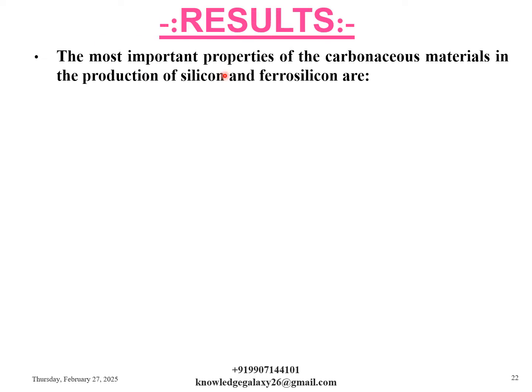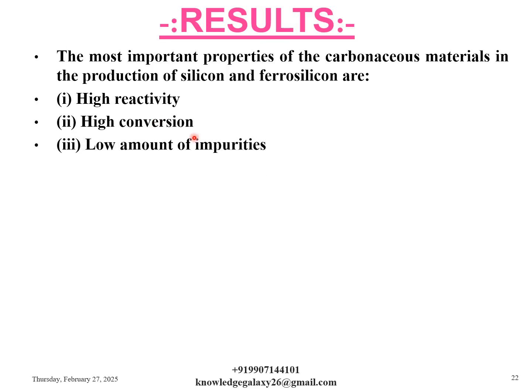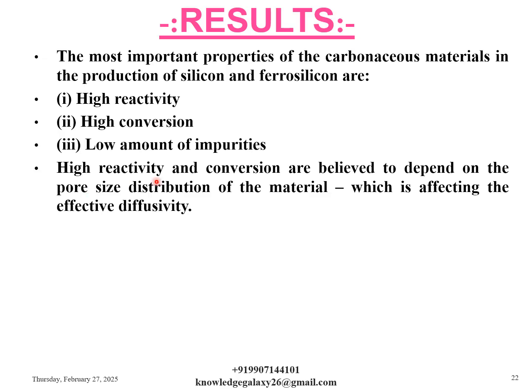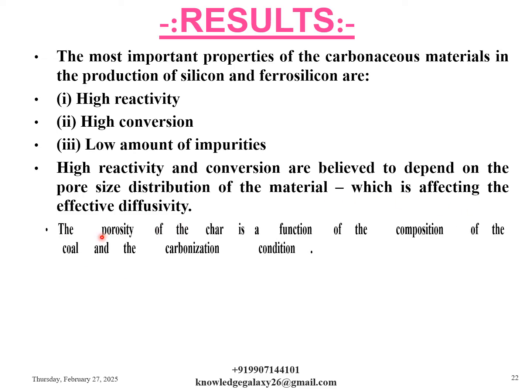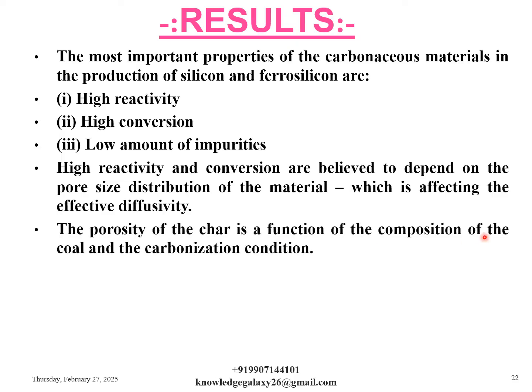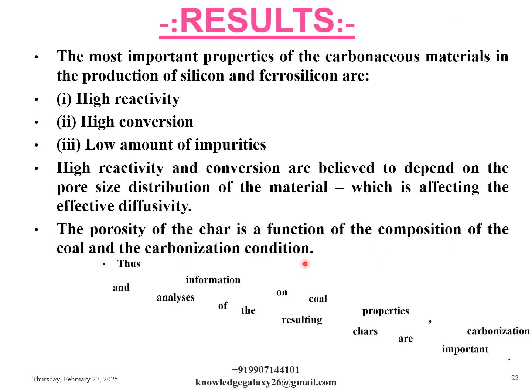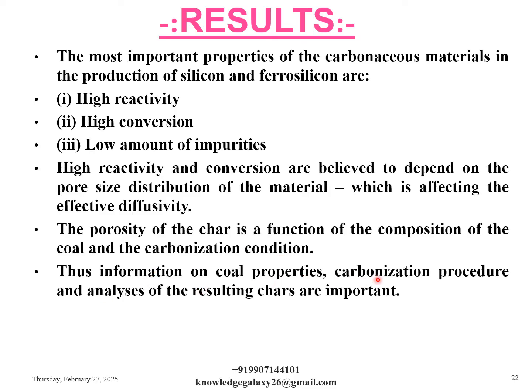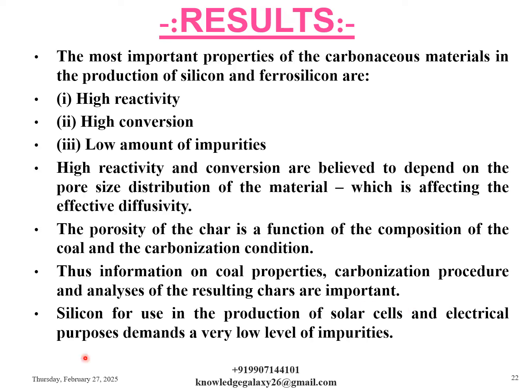So the most important properties of the carbonaceous materials in the production of silicon and ferrosilicon are: first, high reactivity, second, high conversion, and third, low amount of impurities. High reactivity and conversion are believed to depend on the pore size distribution of the material, which is affecting the effective diffusivity. The porosity of the char is a function of the composition of the coal and the carbonization condition. Thus, information on coal properties, carbonization procedure and analysis of the resulting chars are important. Silicon for use in the production of solar cells and electrical purposes demands a very low level of impurities.